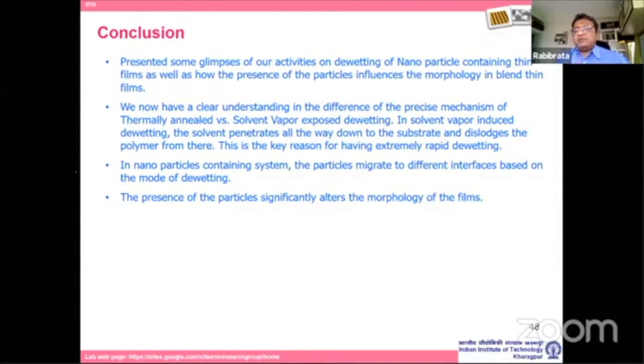And these are model systems. I work on very simple problems: gold nanoparticle, PS, PMMA, no use, no translational value. But let me remind you that this polymer blend work with nanoparticles is very, very closely related to the whole physics of bulk heterojunction solar cells. And that understanding is not there. We still struggle, primarily because they are unable to control the phase separation and the dynamics subsequently during deployment. So the presence of the particle significantly alters the morphology.